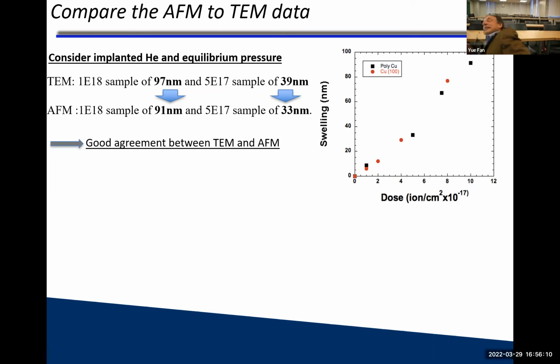But we also compare the TEM. So the other thing we compared is we count the helium bubbles and then say, okay, the helium bubbles are the empty space. And from the TEM, I calculate that we should get 97 nanometer height increase, or 39 at this dose. And from the AFM, I measure 91 and 33. Okay, so close, right? But you can account for the empty space. That's what I'm saying, so that the TEM image agrees with the AFM. Well, that's good. But the question then is, are my bubbles overpressurized or not?